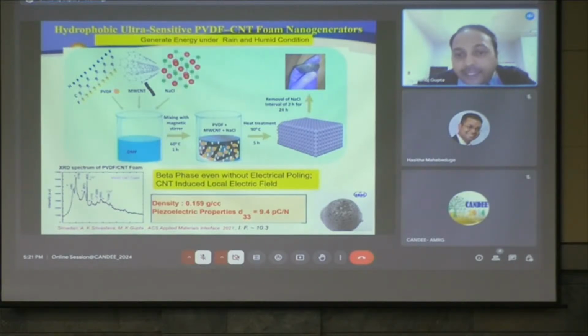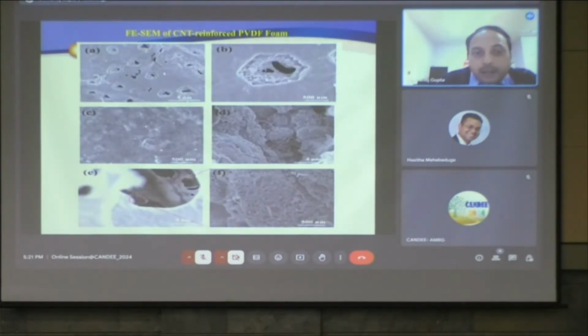So we added NaCl salt. Salt is added with the PVDF and carbon nanotube, and then we immerse these devices in water so that NaCl will be dissolved, and only this PVDF with CNT foam we will get. This is a purely hydrophobic material and also has piezoelectric property, 9.4 picocoulombs per newton. You see, these pores are because of the NaCl, which was lost in the liquid. And this is the carbon nanotube present inside the PVDF matrix, and it helps PVDF create more beta phase, which is very essential for piezoelectricity.